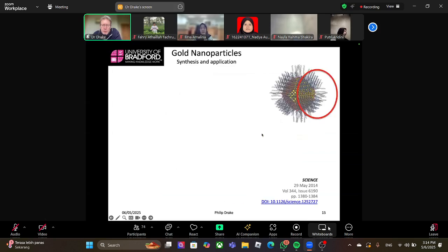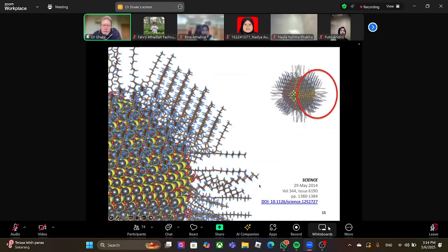So if we zoom in on this surface, these are actually hexadecanoic acid, carbon 16. So there are 16 carbon atoms in a line ending in a carboxylic acid bonding to the nanoparticle surface. So these are the surfactant stabilizing ligands sticking off the surface. This gives the nanoparticle a very hydrophobic surface. So this particle will be soluble in organic solvent, not in aqueous solutions.